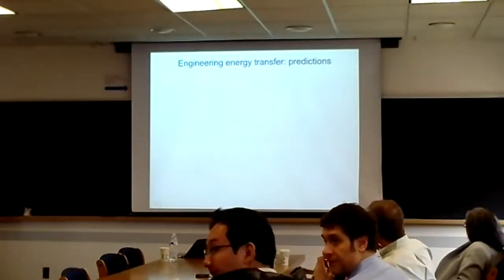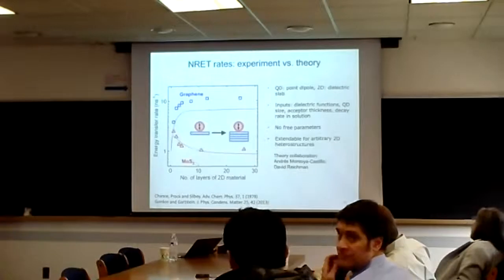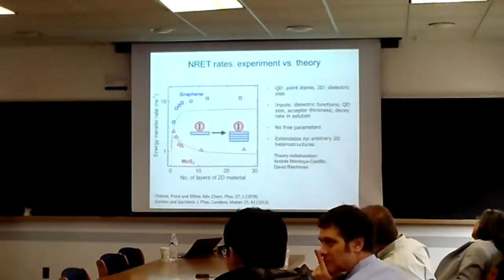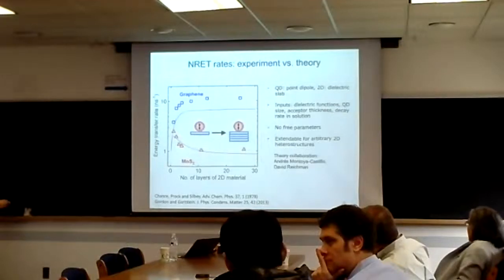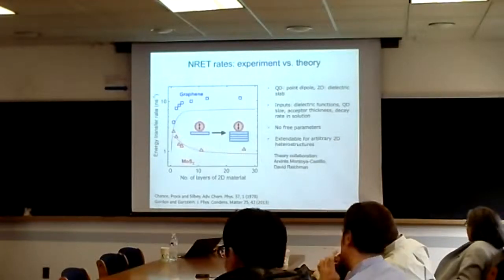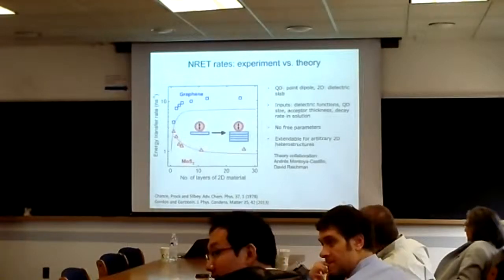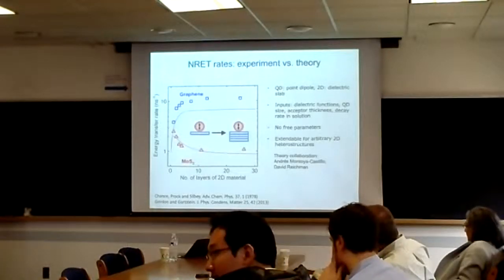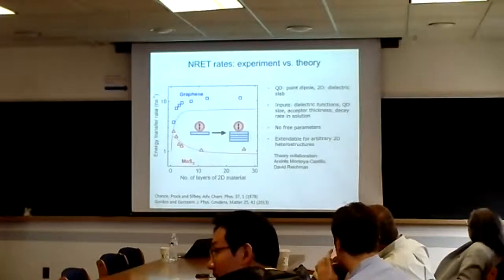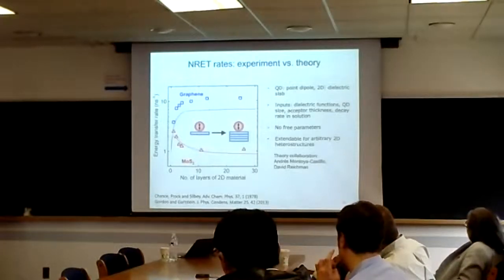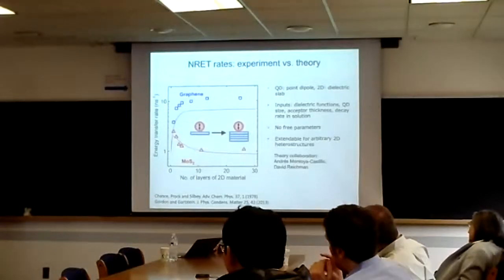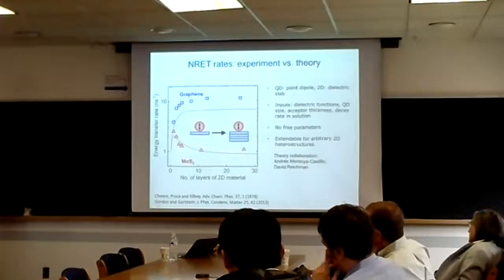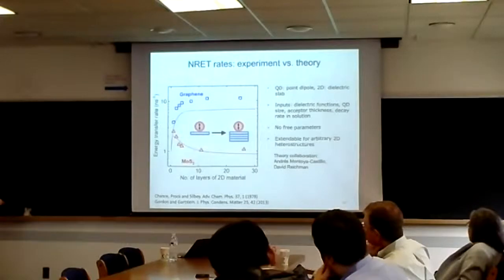Can I ask you about your model? Yeah. Are you really adding layers here, or are you changing the slab thickness? This is just converted to number of layers. We are just changing the slab thickness. So there is no anisotropy in the system? No, there is, because of the dielectric function. I'm supplying epsilon in plane and out of plane, so the anisotropy for that slab is there from that. But otherwise it's really classical. There's only a continuous slab, and that's why it starts at 0 here.